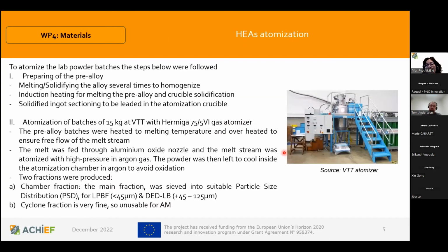So the first step is to atomize the powder. As I mentioned, it was done at VTT. So they prepare the pre-alloy, they melt the elements and solidify several times to homogenize the composition, and they atomize batches of 15 kilos. But the issue here is that they have different fractions. The chamber fraction is the largest one, and these fractions should be sieved into suitable particle size distributions for both processes, for PBF that uses lower particle size and for DED, as you can see here. But the problem also is that we have to disregard the cyclone fraction because it's very fine and it promotes the clogging of the nozzle and it's not usable for AM.